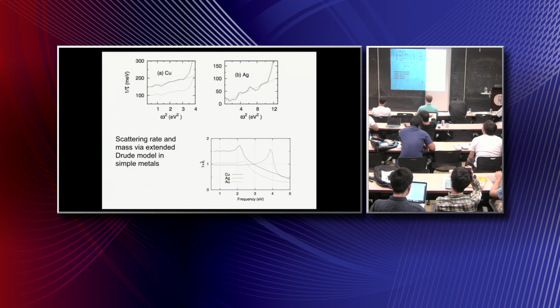And if you do this on the simple old Drude model, you'll find that for the top quantity you'll just get 1 out, right? It's a ratio of a mass to a mass. It's just the ratio to the band mass of the system. And for the other expression, you'll just get 1 over tau, the scattering rate.